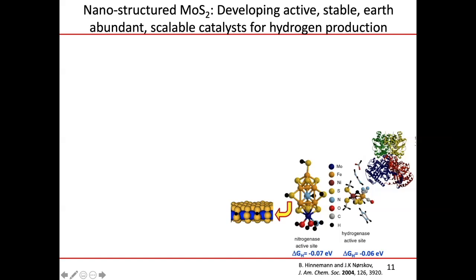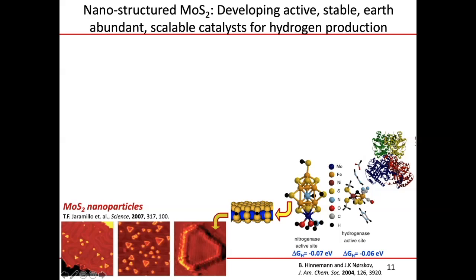Now, this motif at the edge has sulfur, as you can see, decorated in a way that is much more like this sulfur here that is active in the enzyme, compared to, say, the sulfurs on the top and the bottom. And so we went about synthesizing nanomaterials to see if, in fact, the edges were the active site. And they were. All the activity happened at the edges, did not happen on the basal plane.